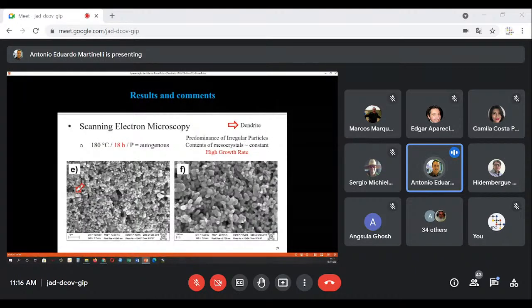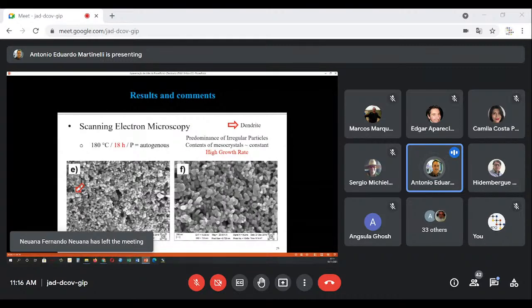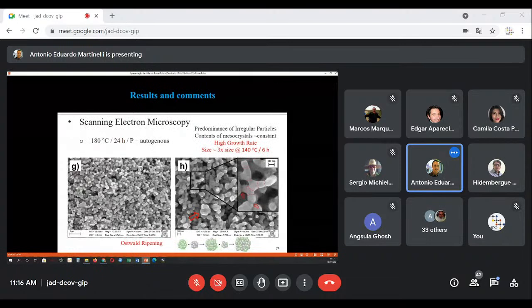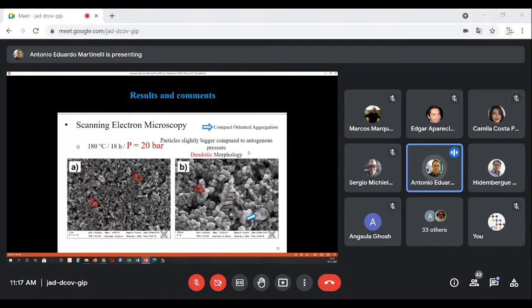18 hours. Now we see something interesting, which is shown by this arrow here: the start of the formation of dendrites, which is a morphology we haven't seen before. 24 hours, again, Ostwald ripening, high growth rate. Now we have 3 times the size that was observed at 140 for 6 hours. And now we begin with pressure.